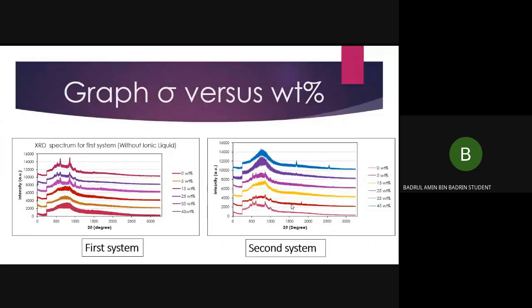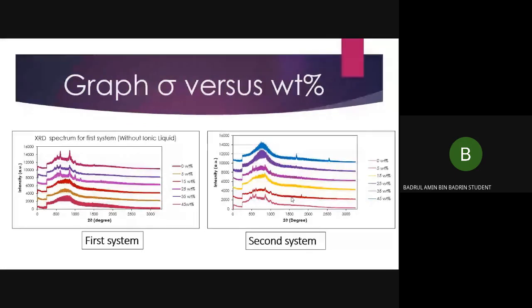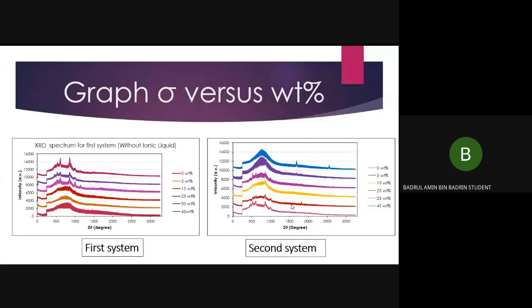So next, the last characterization before dielectric data studies is XRD. From XRD, X-ray diffraction, we want to observe the phases that exist in the system, whether it is crystalline phase or amorphous phase. The broader the area under the curve, the better the sample is. The broader area under the curve represents the amorphous phase, while the peaks, or the mountains you can see from the colorful graph here, represent the crystalline phase, which is not good for ionic conductivity.